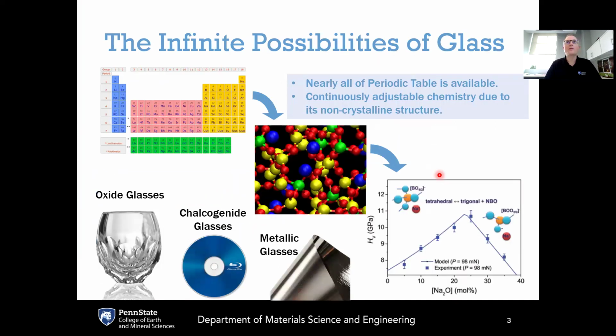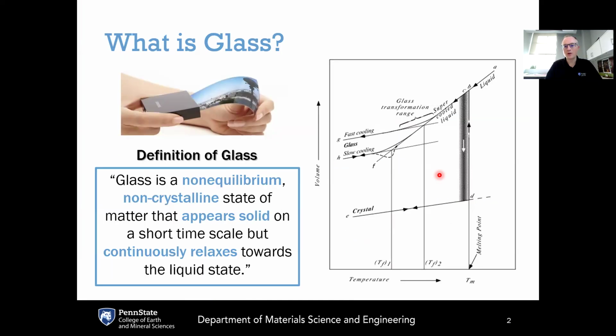So moving forward from a chemical point of view, the interesting thing about glass is that any liquid can, in principle, be quenched into the glassy state if you can cool it fast enough to avoid crystallization. So if we go back to this volume temperature diagram, we noted last time that crystallization takes time, right? It takes time for the atoms to rearrange themselves in the disordered liquid state to form the ordered crystalline configuration.